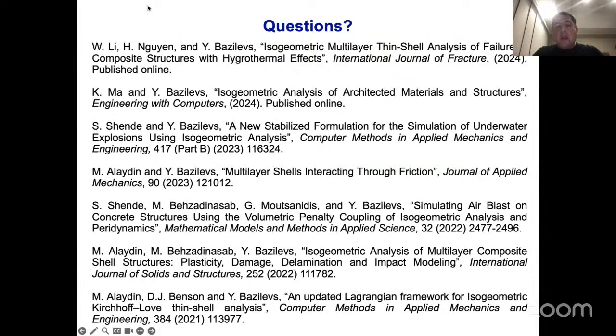What the isogeometric shell approach allows you to do is, first of all, you can afford to use much larger in-plane elements for a couple of reasons. One, Kirchhoff theory doesn't have an issue with transverse shear. And so you can reduce the number of degrees of freedom in plane significantly. And also, you only have 3 displacements per node.